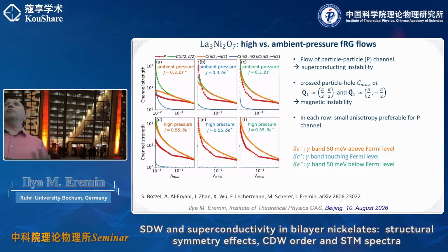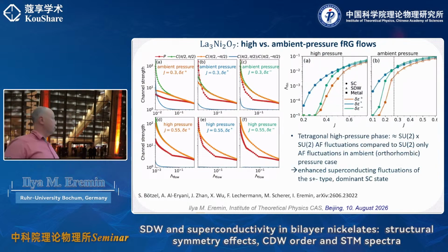So it's again confirming this idea that in unconventional superconductors, you always need to suppress the dominant magnetic instability. And once you suppress it, and in this case, here's a way to do it, which is to go to a tetragonal phase, that will give rise to superconductivity. Okay, so that is also what you can put in this phase diagram that I already presented to you. But that also gives you a prediction.